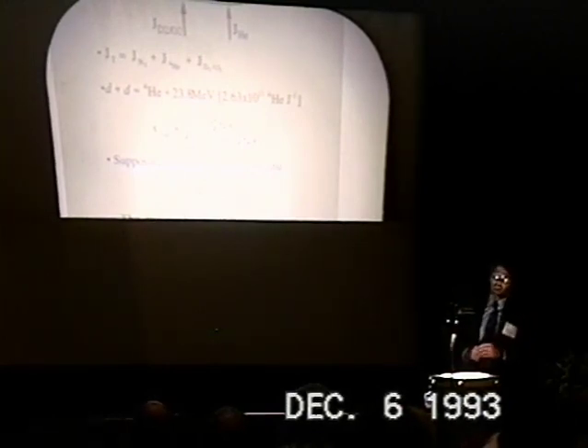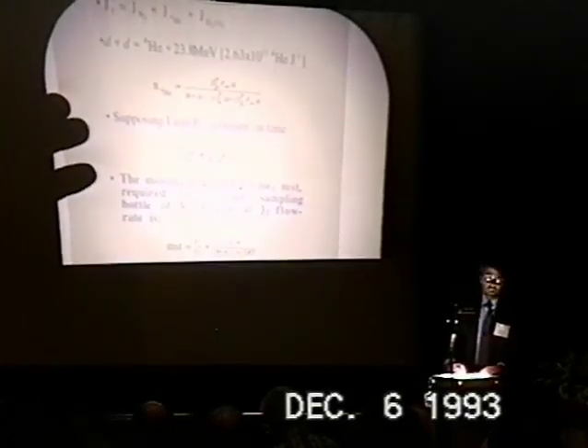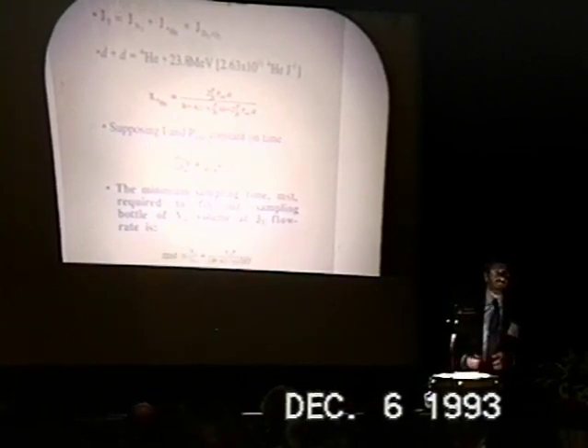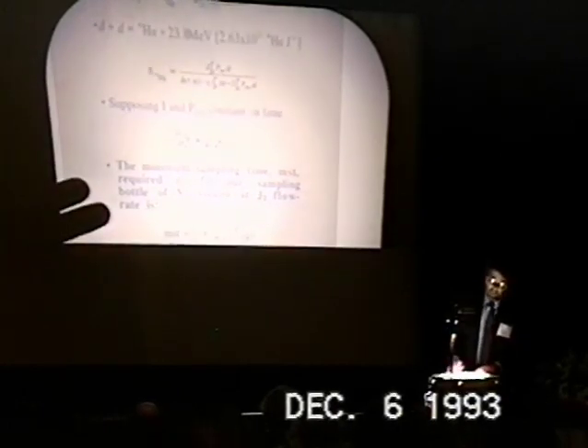If we suppose a short time interval in which we have a constant current and a constant excess power, we have this simple relation in which we can estimate the atomic helium-4 fraction for 1 watt of excess heat. But to calculate the excess power from helium-4 data, it's necessary to evaluate the quantity which we named minimum sampling time, which is the time necessary at our total gas flux to fill our sampling volume. This time depends on the recombination yield of the catalytic recombinator, the carrier gas flux, and also the electrolysis current.